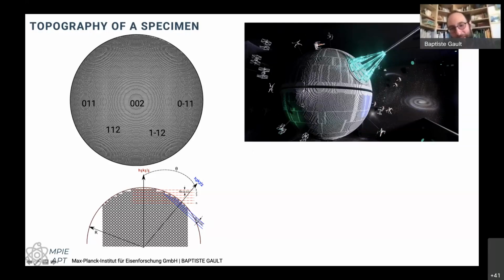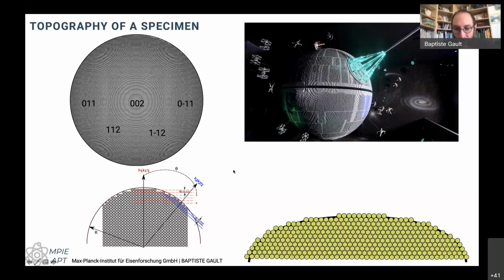But anyway, that's basically what you see here, these different crystallographic directions popping out. And this is exactly what we find inside of the atom probe data as well. So again, when we look at these terraces and the edges of the terraces, we'll have these trajectory aberrations forming.